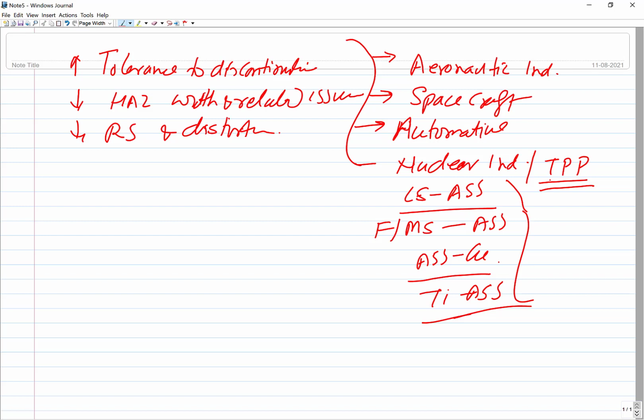Why? I will come to that again, because in thermal power plants the approach is altogether different. It is not the weld zone problem, it is the heat affected zone problem, which is most common in thermal power plants, and it's called type IV cracking. I'll give just one example. You develop a joint, the weld metal is very good. Say one side austenitic stainless steel, another side ferritic martensitic steel. Here you have the joint. You can use any good quality material so that the weld is good. Most hardly will the failure occur from the weld in case of fusion.